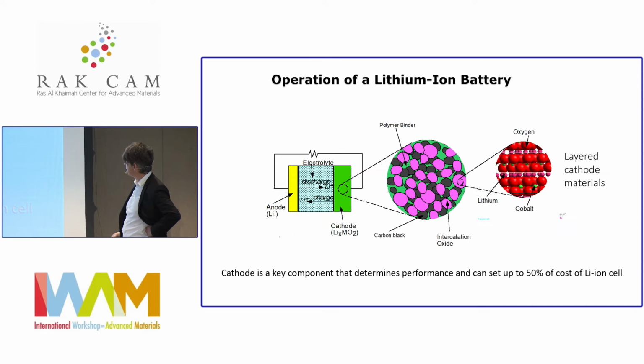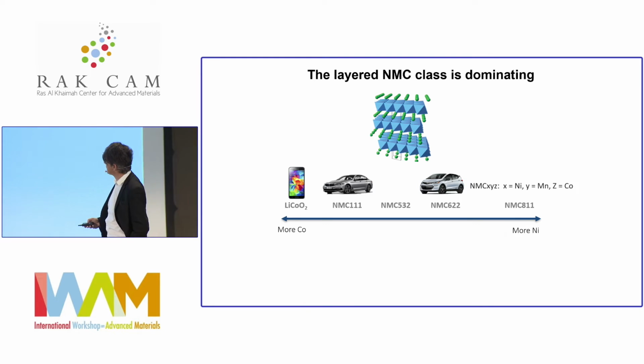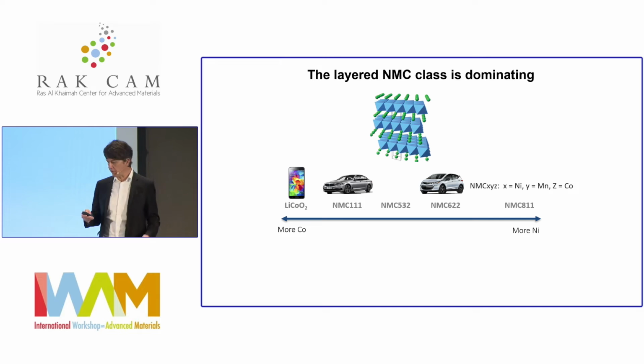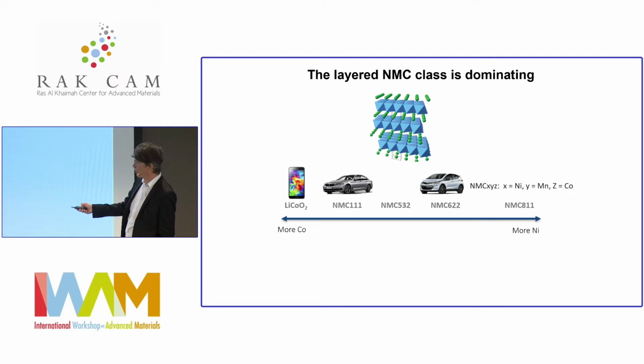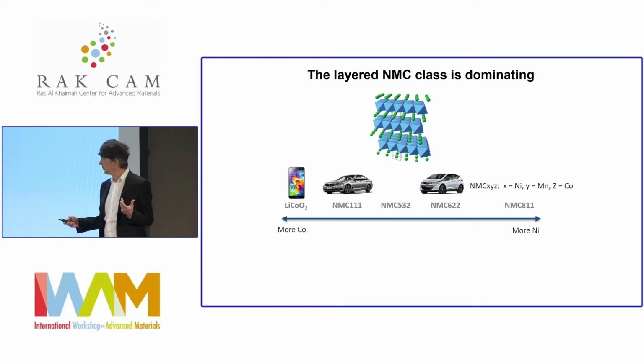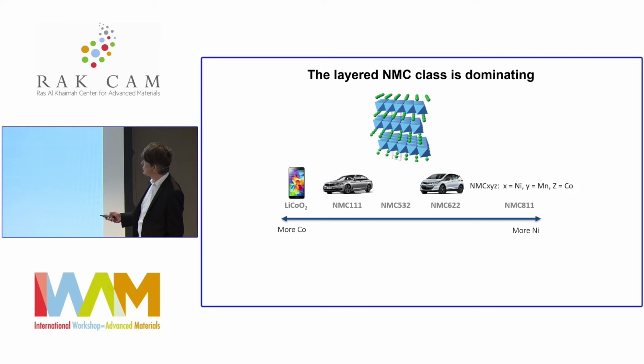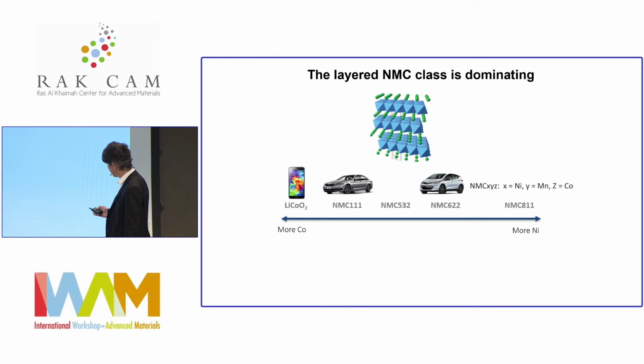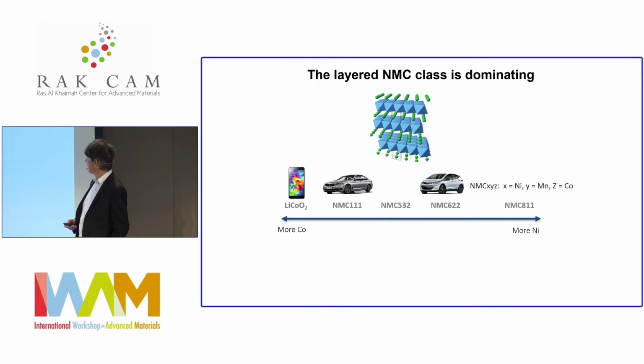And then on the anode side, you tend to use graphite or these days also some amounts of silicon. So this layered class dominates 80% of the lithium-ion industry. Lithium cobalt oxide is what's actually in your cell phone and laptop because of the very high density of lithium cobalt oxide. But as we go to higher applications, the cobalt is being substituted by nickel and manganese, and typically by more nickel. And you know, battery people will throw words around like NMC 111, and all that means is that you have equal ratios of nickel, manganese, and cobalt instead of pure cobalt. NMC 811, the current favorite in the industry, means 80% nickel, 10% manganese, 10% cobalt. So basically, we've gone from using pure cobalt to using mostly nickel, and essentially have turned one problem into another.